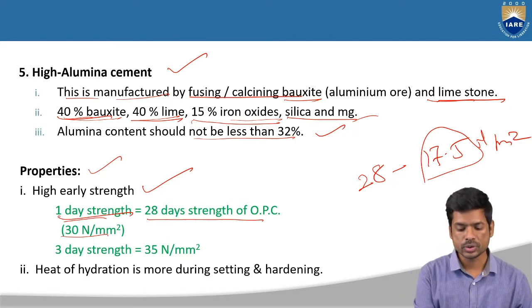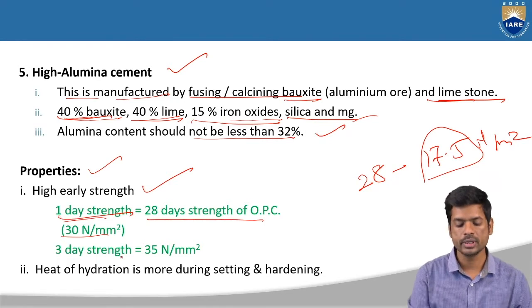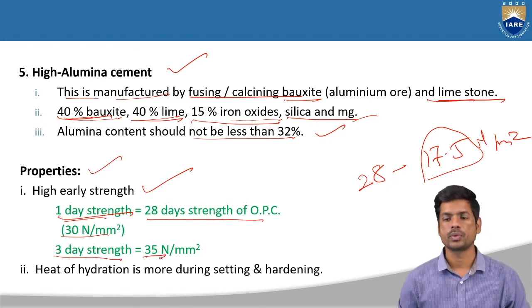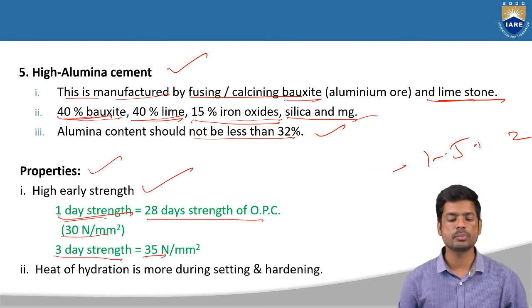Coming to the 3 days strength, if you check the compressive strength after 3 days, it will be around 35 Newton per mm square. This is the strength achieved by high alumina cement after 1 day and after 3 days. That is why we call it a high early strength cement.